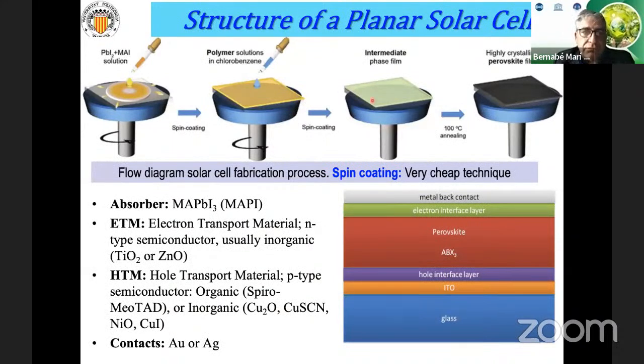Well, this slide shows the flow diagram for the solar cell fabrication process, and we prepare this in our lab. And this is basically spin coating. So we have our sample here. We deposit the solution. The system is turning. Then we add some chlorobenzene, which is called an anti-solvent, in order to control the crystallization. And then we heat a little bit, and we have the perovskite.